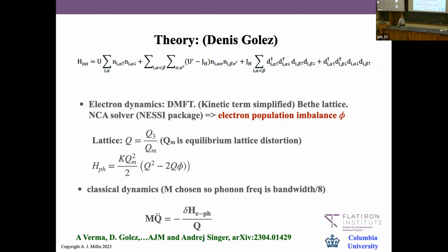Everything we know says that within factors of 2 or 3, they're reasonably good at getting you to a sort of pseudo-equilibrium state. So if I make my electromagnetic pulse and populate the upper band in some way, within a ballpark of 5 femtoseconds the electrons will relax to a pseudo-equilibrium state described by some temperature, but still with this population imbalance. Within factors of about 2, they're reasonably good at that.